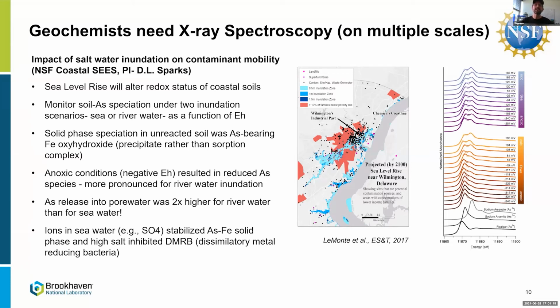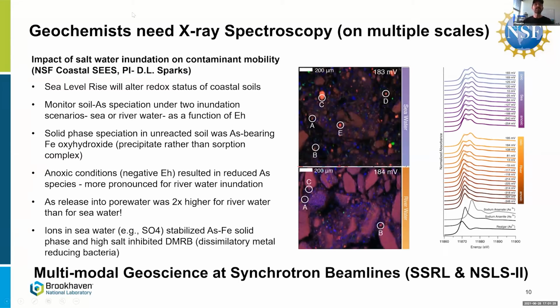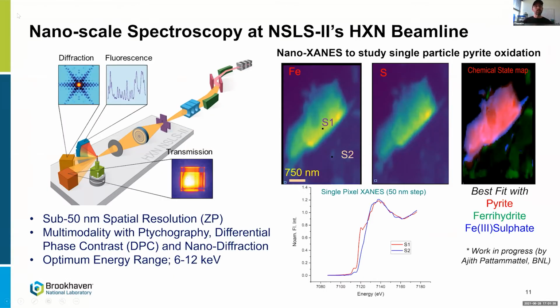What was so cool here is we needed to use micro-XAS to really understand the bulk XAS. And we did this experiment across facilities as well. So this was done partly at Stanford and partly at the NSLS-II, drilling down to that finer scale. Which leads me to an example that I want to tell you about at HXN, which is our nanoprobe beamline that routinely delivers less than 10 nanometer resolution with the multilayer Laue lenses and less than 50 nanometers with the zone plates. And you can see they have multiple modes of contrast here: diffraction, fluorescence, transmission. So a lot of ways of doing imaging and getting contrast through those modes.